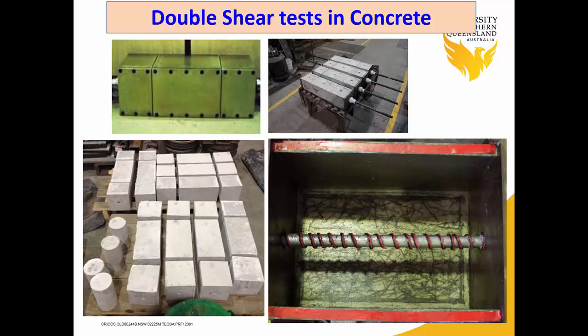In order to simulate field conditions, where you have strata, pretension and grout around the sample, the double shear test was developed. This picture shows the double shearing box, and here you have the concrete sample for double shear testing. Double shear testing consists of three concrete blocks, two outer ones and the middle one, which is bigger. There is a hole in the sample where the fiberglass goes inside and is encapsulated using the hole on top of the sample.